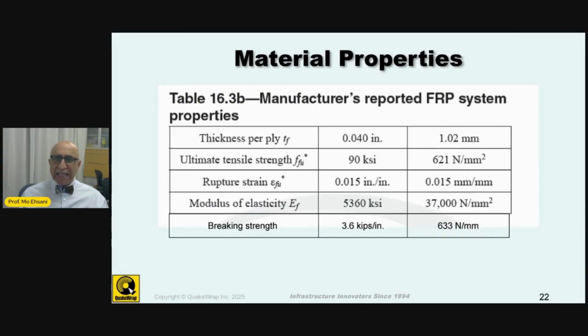And the summary of the material properties that you would use in your design, the most important ones are the thickness of every ply, like this carbon fabric, maybe 0.04 inch, its tensile strength, the modulus, or the strain at failure, 1.5% strain, for example, in this case, and modulus of elasticity.